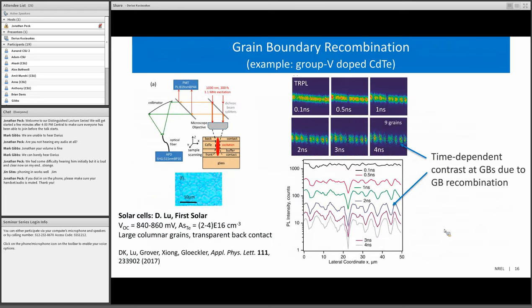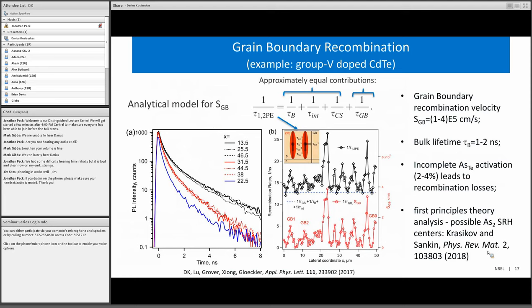When we look at the solar cells, we got these excellent samples from First Solar, where we have large grains, arsenic doping, so that the doping here is above 10 to the 16th, high voltage, and very importantly for this measurement, a transparent back contact. The luminescence graphs on the right show this time-dependent contrast, and the linear intensity profile shows how luminescence changes over time. The dark areas that appear in these images are grain boundary recombination, and when we apply the analytical model for this analysis, we see that the grain boundary recombination is as high as 10 to the 5th.